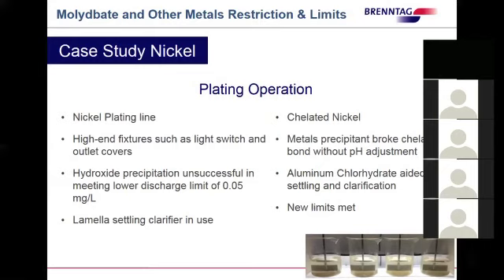In this case, I looked at all three of the previous metals precipitants: the diethyl dithiocarbamate, the dimethyl dithiocarbamate, and the trithiocarbonate. I found that the trithiocarbonate was very touchy, because if you overfeed it, you can actually do the exact opposite of what you're trying to do, and you'll disperse the metal. The dimethyl dithiocarbamate performed much better. The diethyl dithiocarbamate performed as well, but the DMDTC really showed itself to be the one to use. However, I was creating a very fine floc, so I used a little bit of aluminum chlorhydrate to create a larger floc so that our flocculant polymer could then grab it and settle it out. And as a result, we met our new limits.